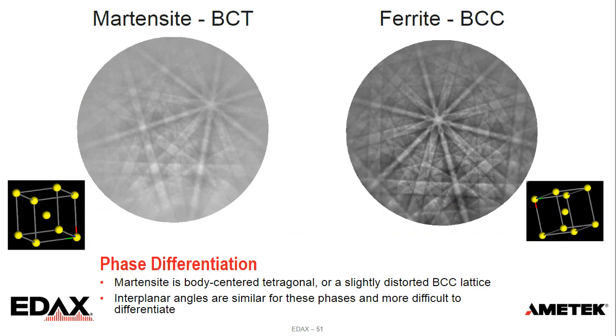And then this is one we said we would talk about, a question that came in before the webinar started. This is a question that's been around for EBSD for a long time: how do we differentiate something like martensite from ferrite? Martensite is body-centered tetragonal, a slightly distorted BCC lattice. It's distorted from the temperature change and phase transition from austenite, ferrite into martensite, and how that strain is retained in the unit cell. So basically the cube is just slightly changed. One of the things that's tricky is that the 'slightly' can depend on a lot of things. It's not always uniform in your alloy. It can vary with local carbon content. And so the interplanar angles between these phases are very similar. It can be more difficult to differentiate.